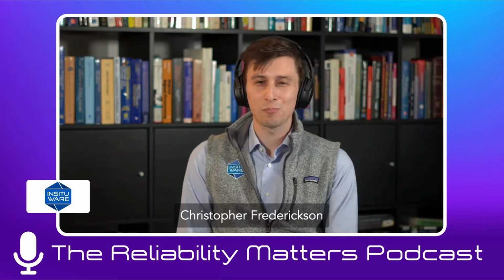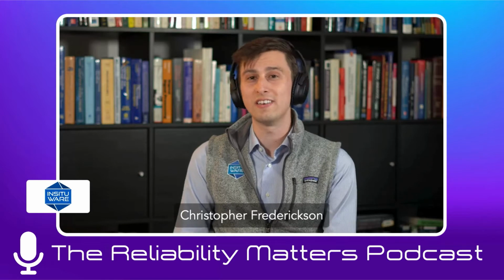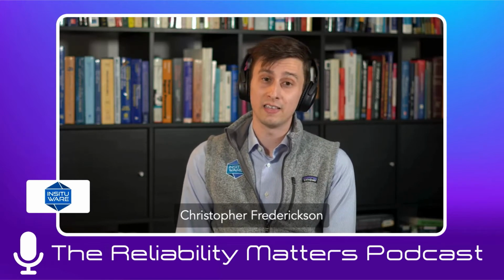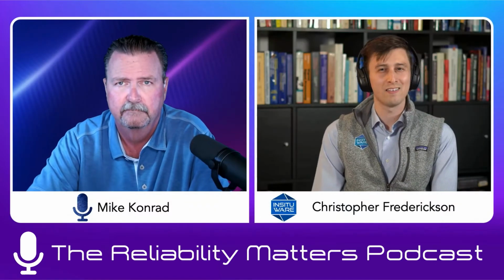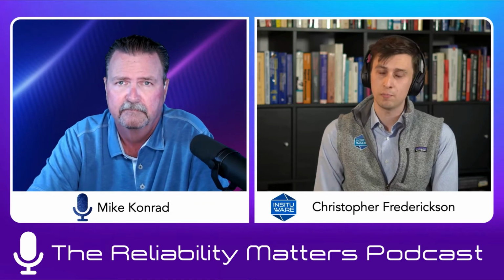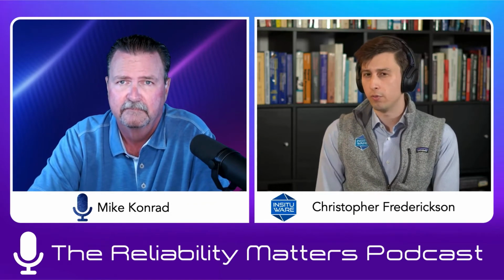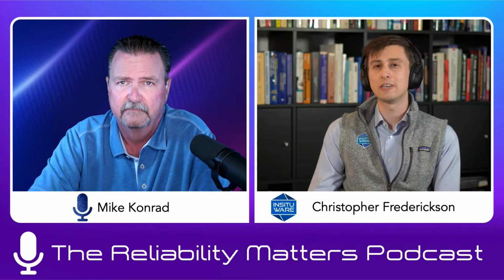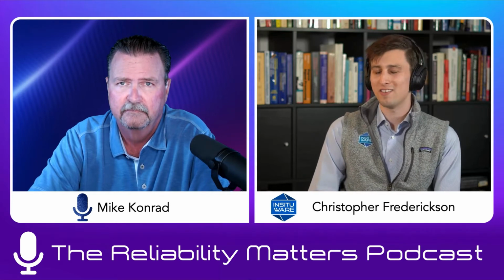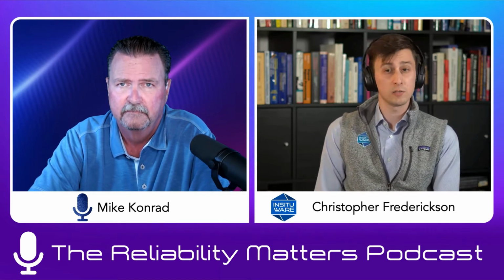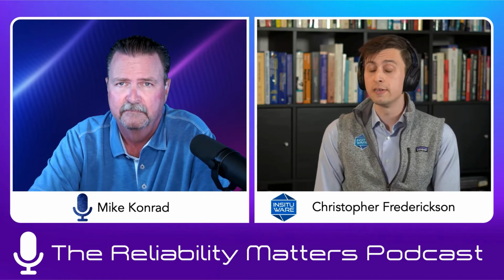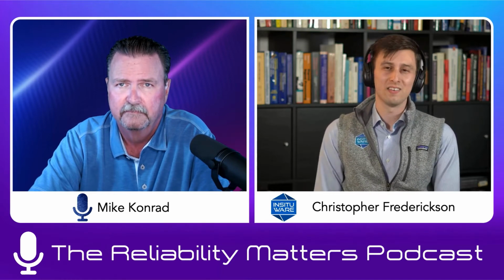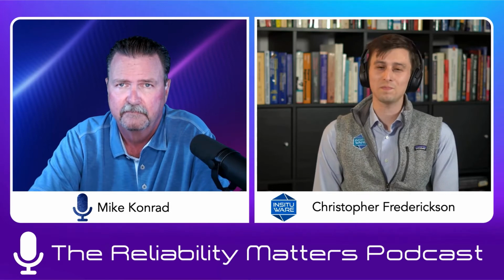But there are plenty of areas where you can run into issues where you start to deviate from that. Shipping, for example, is very much an uncontrolled process at times. You can't track and monitor what's happening to the paste during shipping, so you have a little bit less control there. Same as during handling. If you're following everything perfectly, these materials really are quite good. But there are always traps along the way. Yeah.